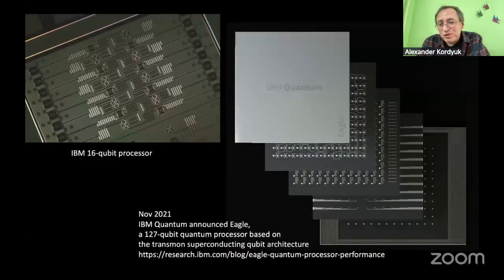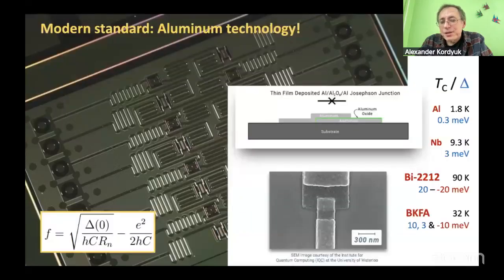And in order for quantum computing to work, you need at least several thousand, 10,000 or 100,000 qubits correlated. And at the moment, it is just a few hundred, right? It seems a serious obstacle. I think evidently the problem is the small superconducting gap. And the superconducting gap here is proportional to superconducting temperature, and the technology here is well elaborated, aluminum technology. It is good in the sense that it gives you very reproducible results, because aluminum is easily covered by a predictable layer of aluminum oxide. And it is an insulator, and it is easy to make a Josephson junction, a tunneling junction, let's say, with superconductor, but between two superconductors.